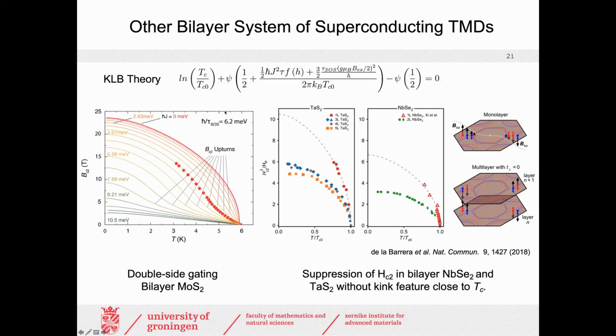And once this is very big, then the system gets coupled. But if the spin orbit interaction is very, very big, this is because interlayer is more or less a constant value if you put these two layers together, and if it is very big spin orbit interaction in the valence band, that is the case of tantalum disulfide and niobium diselenide, then you don't have this kind of kink behavior simply because this is too big, and you need to have a similar interlayer interaction start to compete so that you can see a kink behavior.